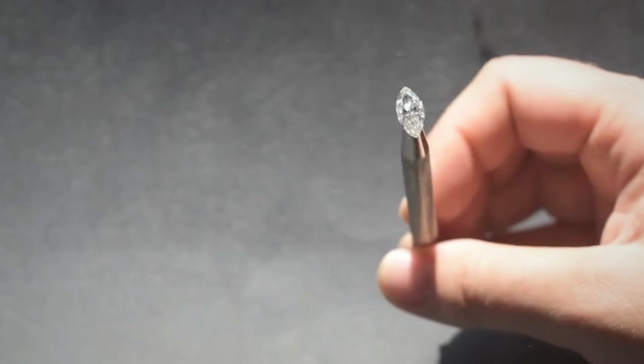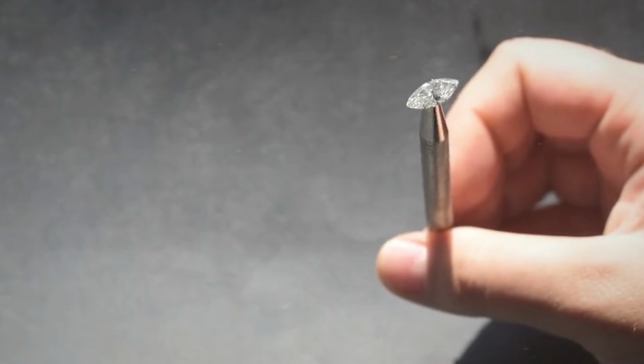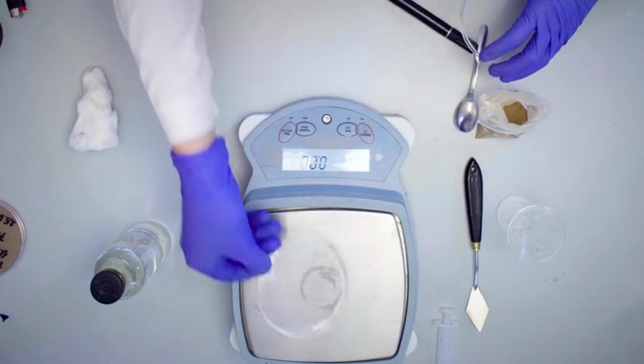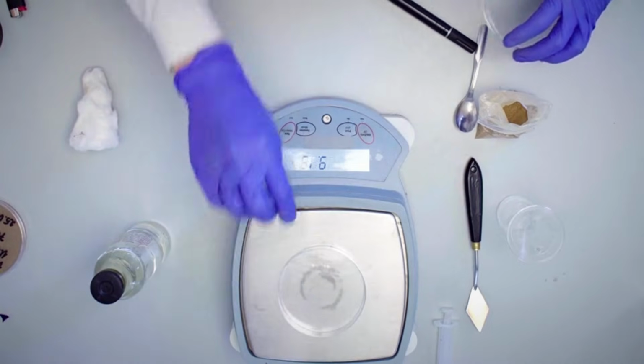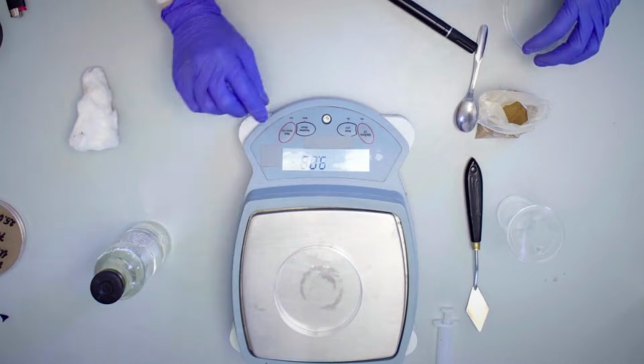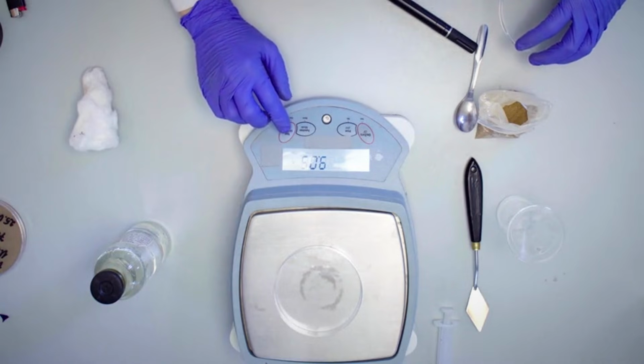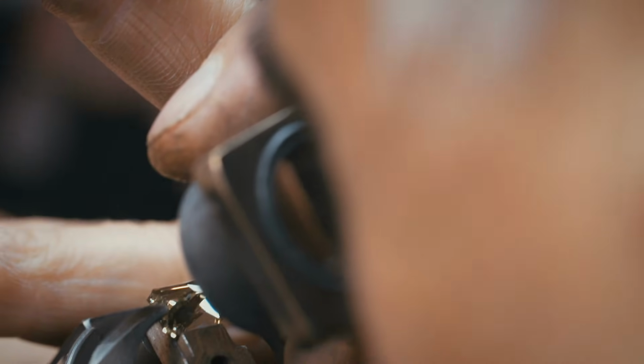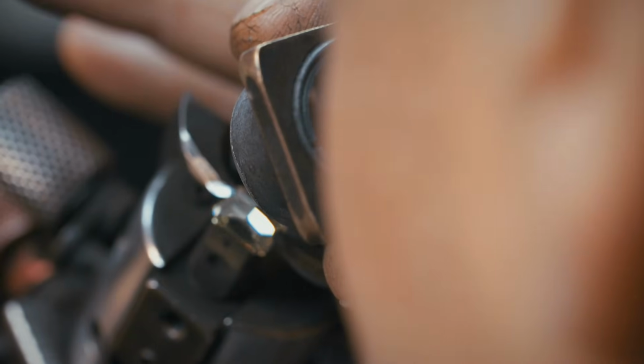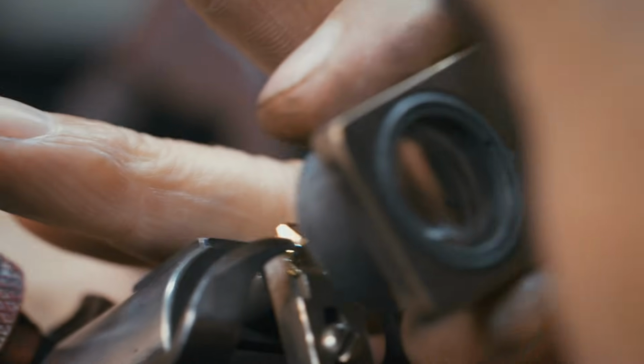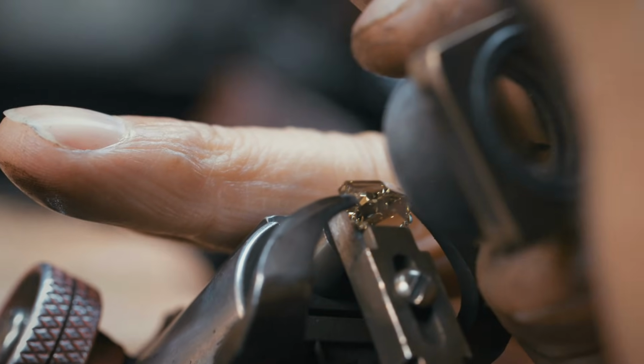For best results, use a freshly charged or calibrated tester, and allow both the stone and probe to reach room temperature before beginning. Some testers now include dual-mode functionality, switching automatically between thermal and electrical conductivity tests to address moissanite interference. A critical upgrade, as we'll explore next. But even with basic models, thermal testing filters out most simulants and validates further investment in verification.